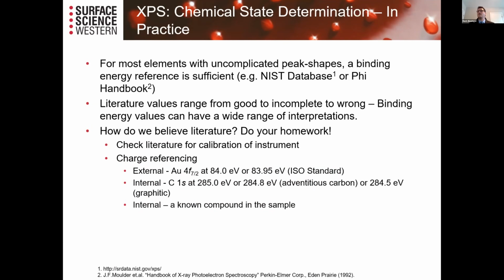So, how do you believe the literature? You have to do your homework. Some of the things you can do, you can check the literature for the calibration of the instrument. That's a big issue. What they're using is charge referencing. So non-conductive samples will build up an electron charge on their surface that has to be compensated for. You have to take those things into account. So are you referencing to an external standard such as gold, internal standards such as the adventitious carbon or a known component of the compound, etc.?